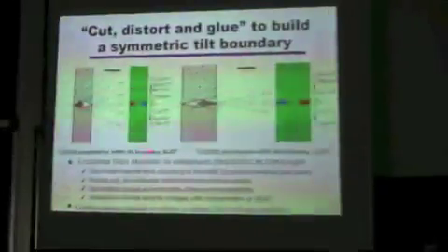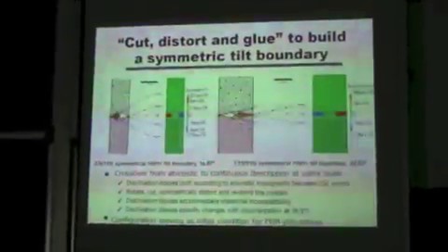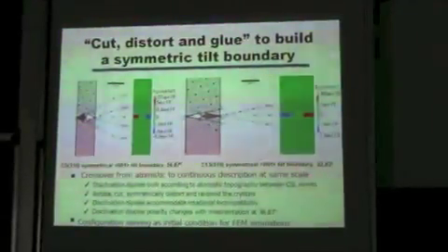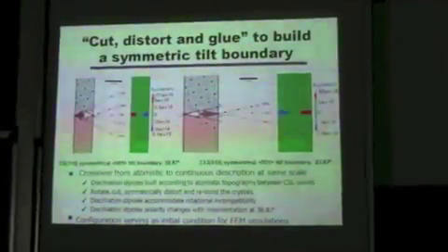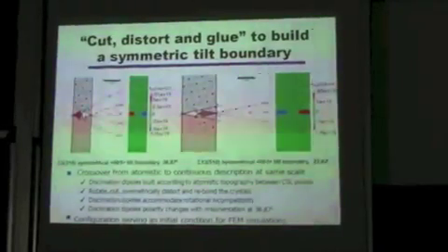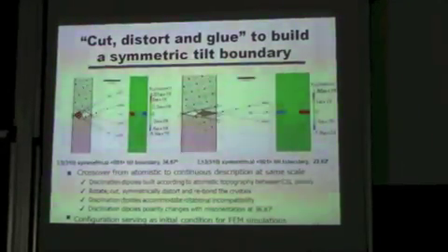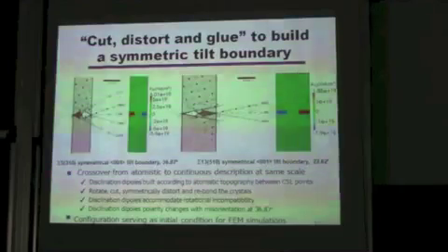This one is for a misorientation of about 36 degrees, and the second one is for 22 degrees. So take two crystals, one gray crystal and one red crystal, rotate them, so the rotation is already there. Then cut the crystals according to these broken lines here. For the gray one, this one, and for the red one, the other one, obviously.